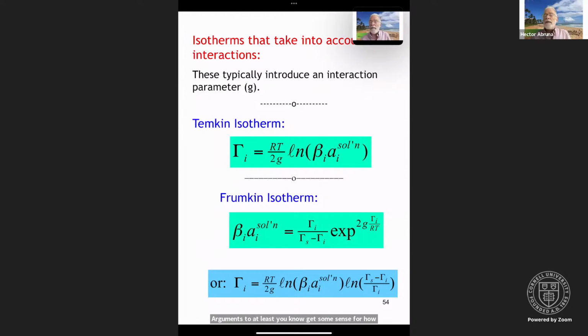Now, as we mentioned, the Langmuir isotherm assumes no interactions. And then there are certain isotherms that can take these into account, and this is typically done by introducing an interaction parameter, typically G. There are two isotherms that are typically used. The Temkin isotherm,